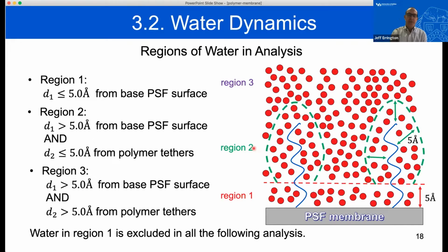Going into this, we wanted to be able to say something about water in the vicinity of one of the tethers versus water in the vicinity of the base surface. And so what Ichi did was to come up with an approach in which we identified different regions. Region 1 is water in the vicinity of the base polysulfone surface, so it's water that is within 5 angstroms of one of the heavy atoms associated with the base membrane. Region 2, which is where most of our focus was, is water that is within 5 angstroms of one of the heavy atoms associated with the polymer tether, but at least 5 angstroms away from the base surface. And then region 3 is everything else. You can think of region 3 as somewhat like the bulk water associated with the system.